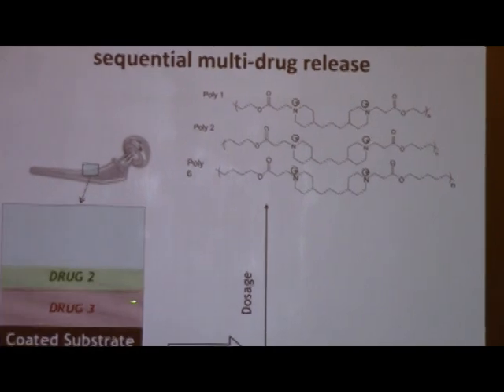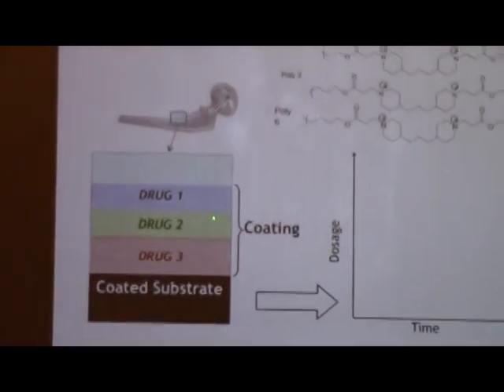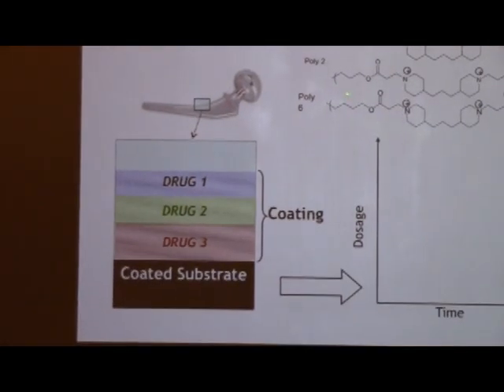You can imagine I can build up layers not only of just one drug, but of 2 or 3. I can even generate films in which they're stacked so that I have drugs 1, 2, and 3 in some sort of surface-based order. What this means is that, first of all, depending on which polymer I decided to pair with which drug, I will have a release profile defined by the degradation rate of that polymer. So now I can have more than one different release rate.